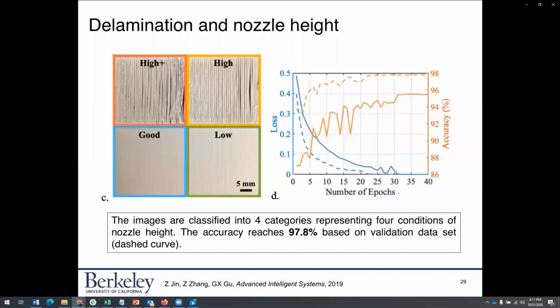You can imagine if it's very high, your layers won't have very good adhesion with each other. But if your nozzle is too close, then the layers will be very squished. So it's really about trying to achieve this optimal nozzle height, to prevent these issues from happening in real time, and then correct for them if they do happen.